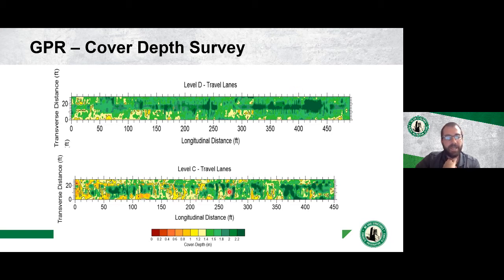And so we're going to get better protection to the rebar on level D than we are on level C. And level C being closer to the level on grade, which is level A, there's going to be more salt exposure potentially on level C than D. So we would be worried about the service life of level C versus level D because there's a lot more lower cover on that structure than other locations.